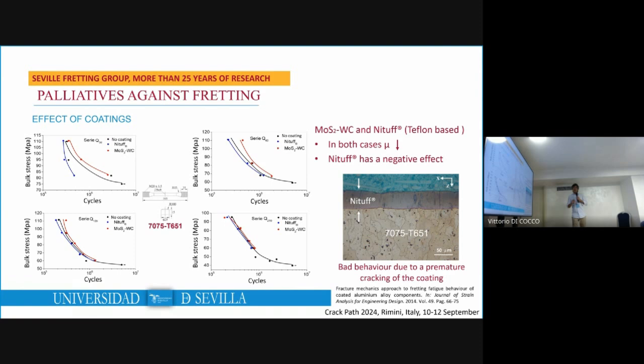The first thing that we saw in this test is that, independent of the fretting regime, the Teflon coating always produces a bad result when compared with the uncoated cases. Also, in the case of molybdenum-based coatings, the behavior was good only when the tangential load was low, and also in the high cycle fatigue regime. Okay, we also observed that in both cases, the coefficient of friction is lower than in the as-machined case. And we observed that the bad behavior produced with the Teflon was due to a premature breaking of the coating.